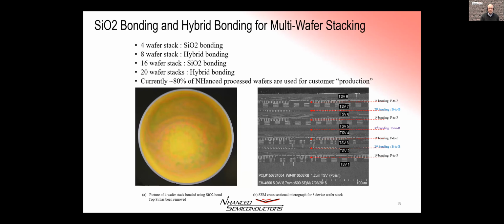We can do very high stacks. On the right-hand side there, you see an 8-layer stack. The TSVs, which are the little vertical lines, are a micron in diameter and about 6 microns long. Those layers are, I think, about 12 microns or so, probably 14. This is 8 layers of metal plus the bond pad, which is at the very top, right above where it says TSV8. That's an aluminum metal pad that's making contact to the via, which is to the right of that.